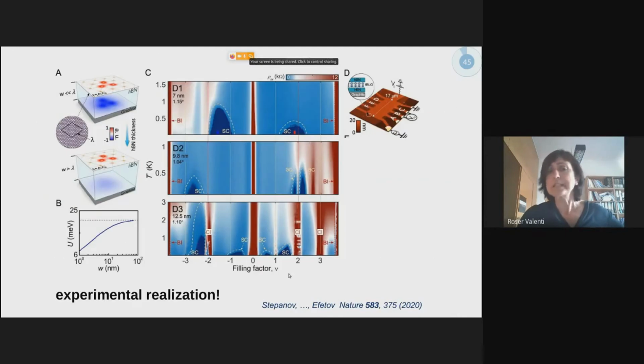And there are very recent experiments in the group of Dmitry Efetov where they indeed find these predictions: by separating the layer, this twisted graphene, from the metallic layer, which here is graphite, one observes the presence of a correlated insulator, as they call it. So there's an increasing of the Coulomb repulsion. So you can now manipulate the strength of correlation of the system by playing with the twisting angle and also with the distance to your metallic layers, and ask whether superconductivity is in fact competing with this correlated insulating phase, etc. So with that, I come to the end of my talk.